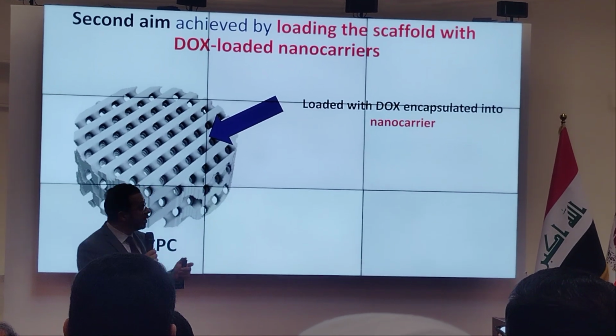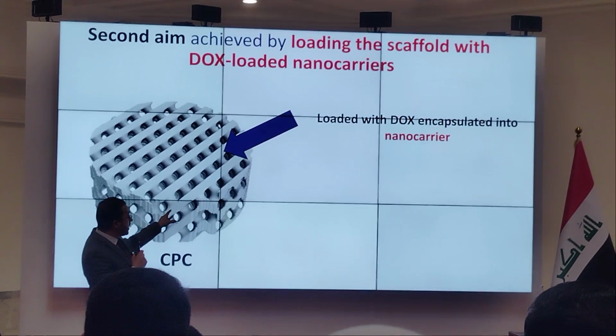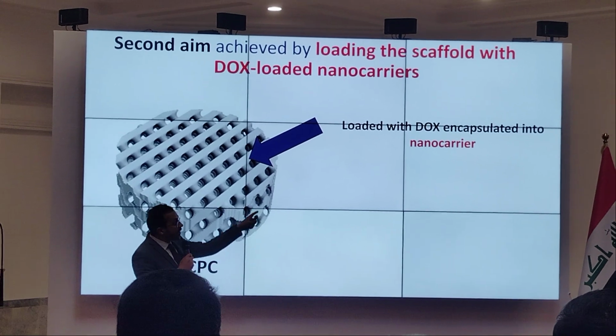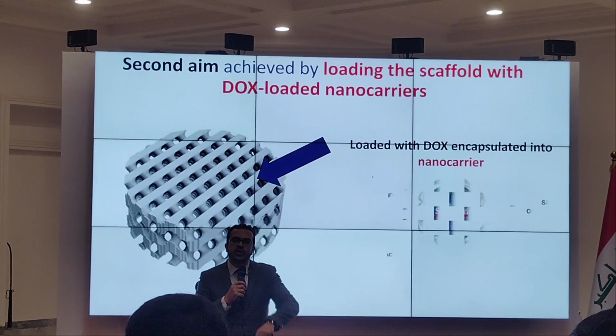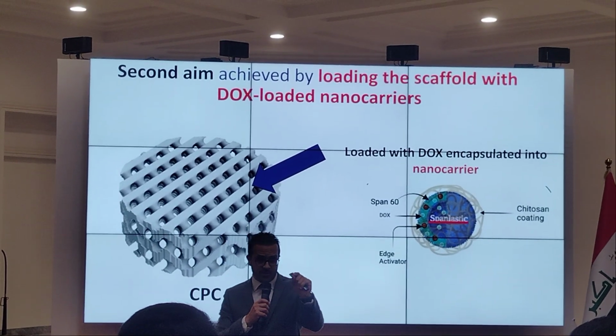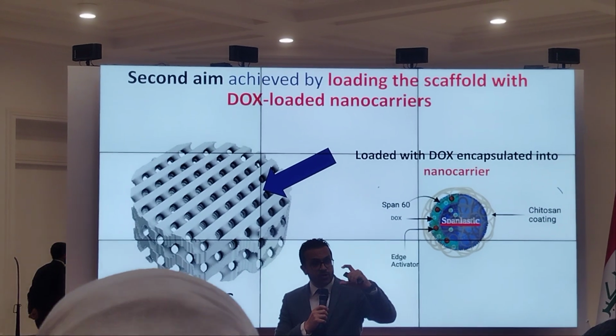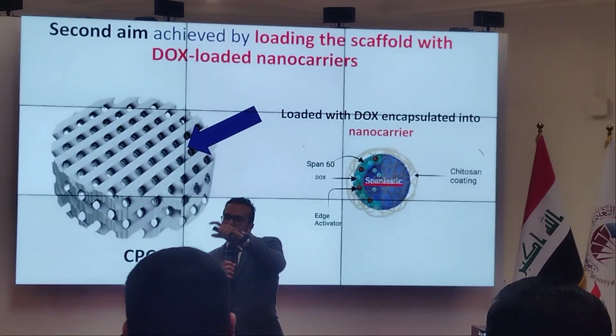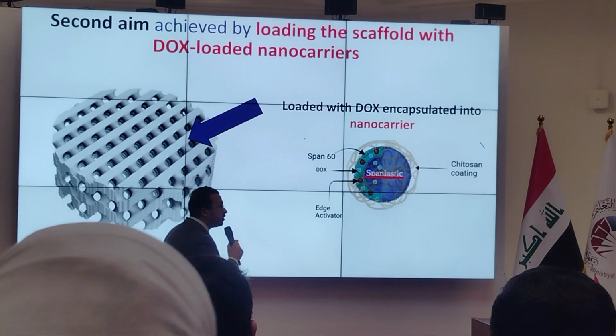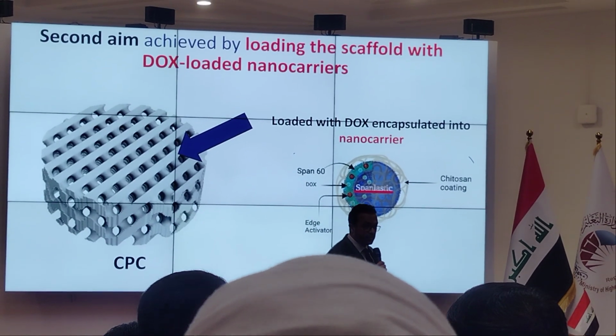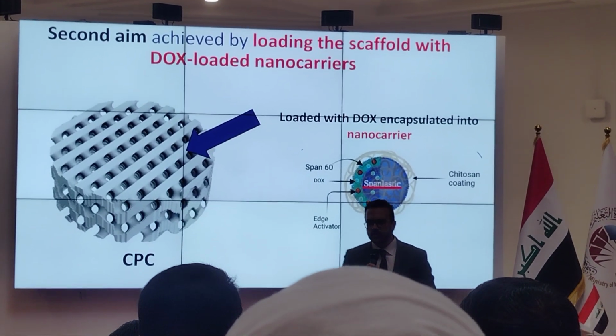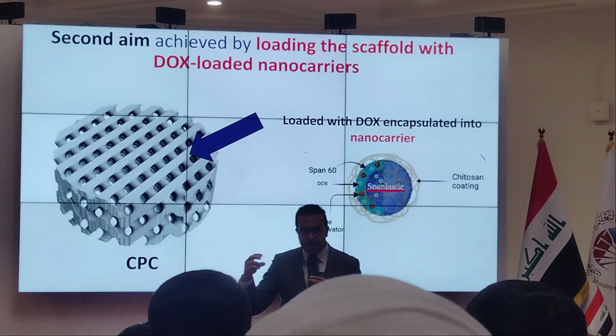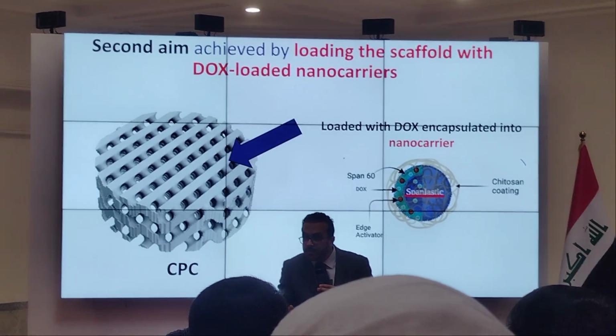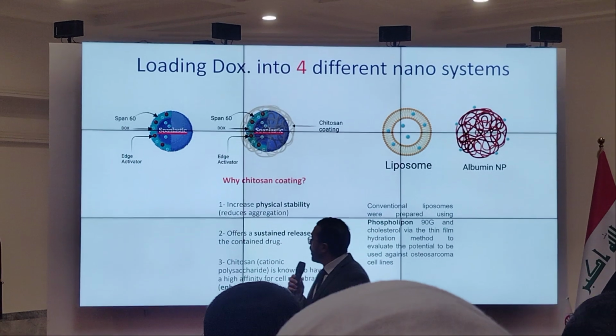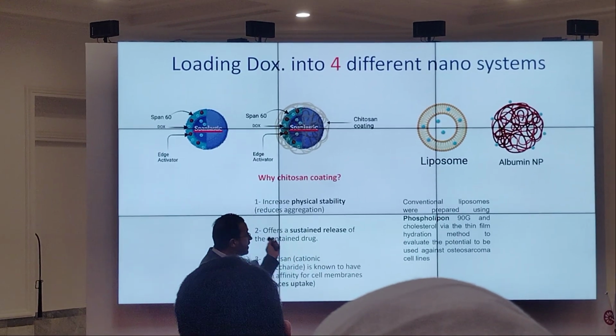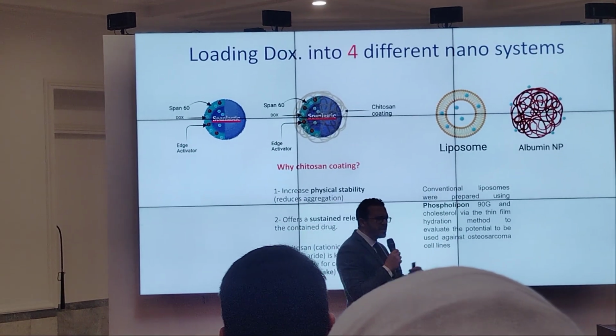So we didn't load doxorubicin directly into the scaffold, but we encapsulated doxorubicin into nanoparticles. So we put doxorubicin, the chemotherapeutic agent, into nanoparticles, then loaded these nanoparticles onto our scaffold. So why did we do this? To increase uptake by cancer cells and to protect the normal mesenchymal cells in bone. Actually, we have compared several nano carriers. I will not spend much time here.